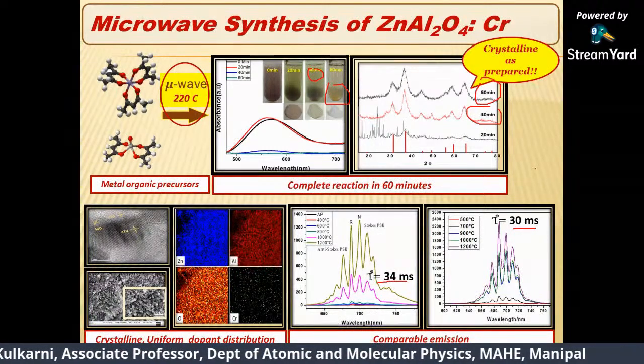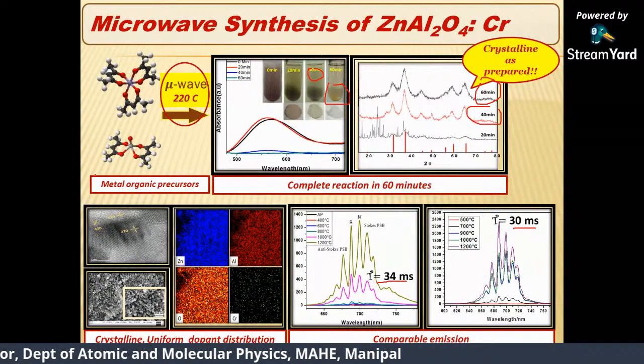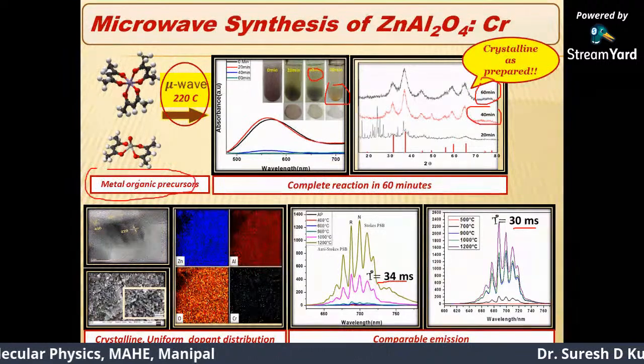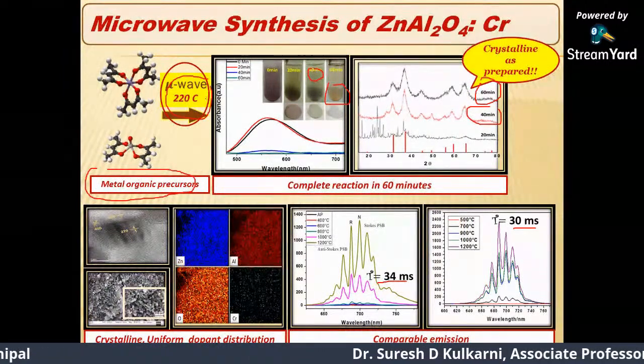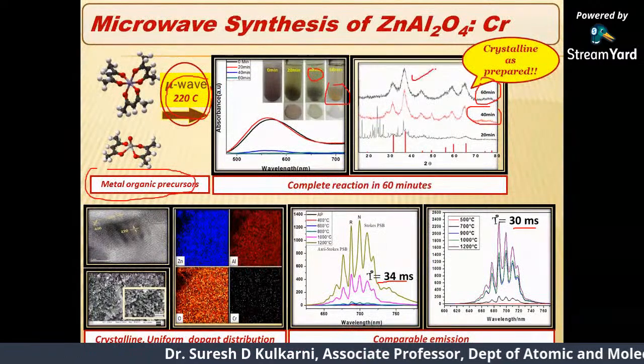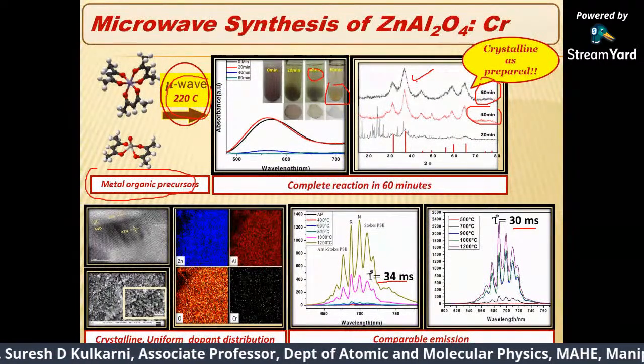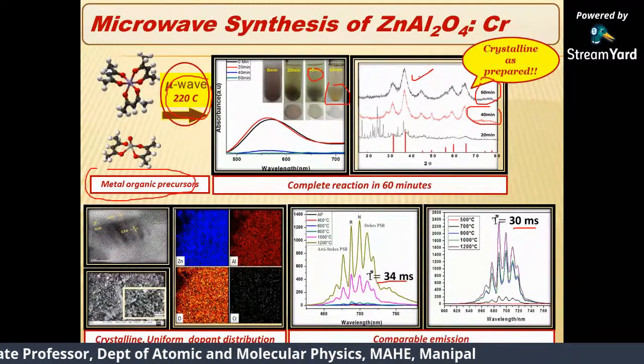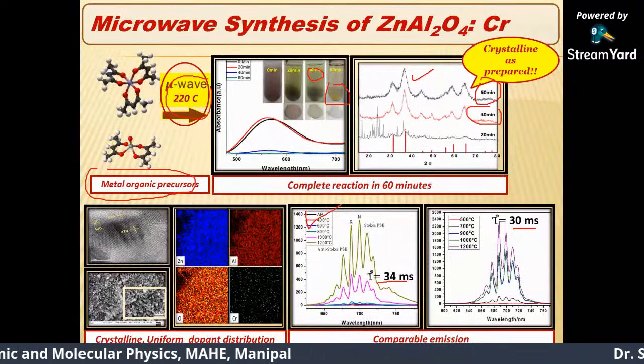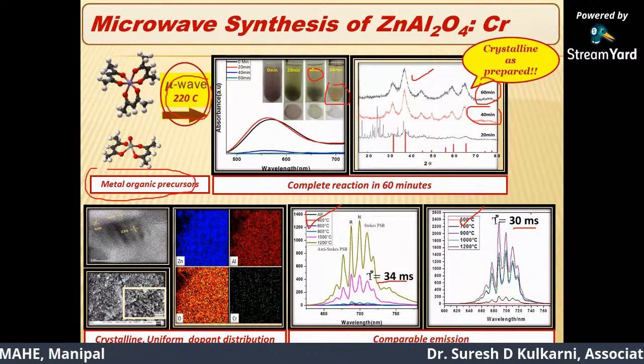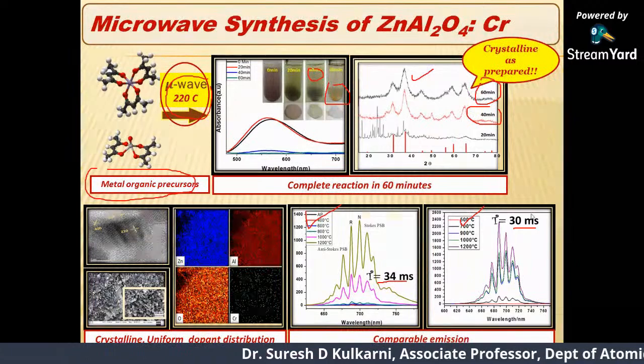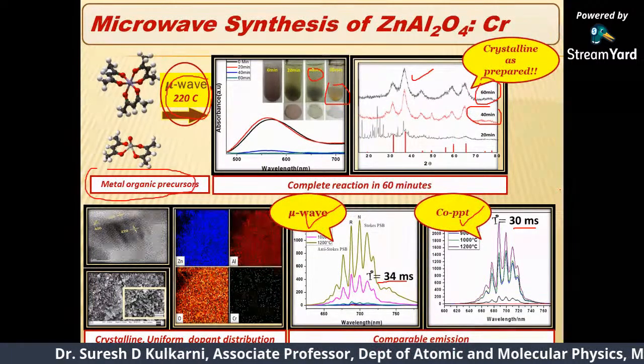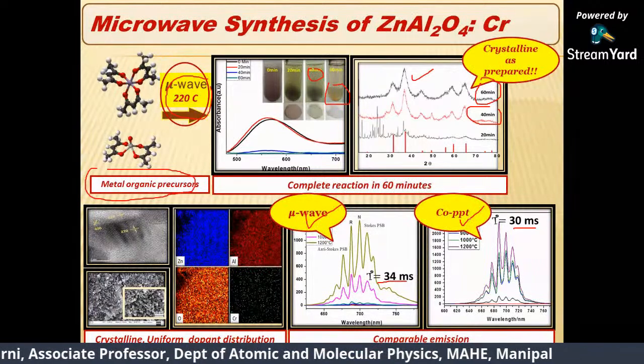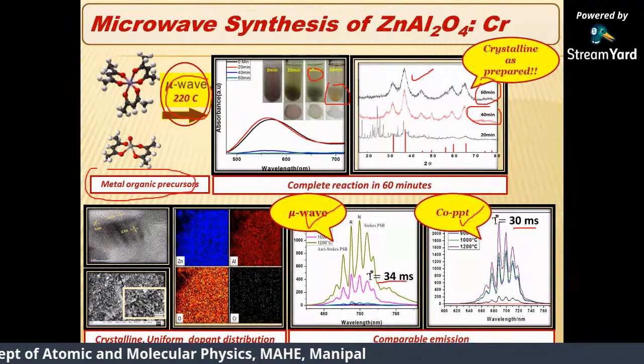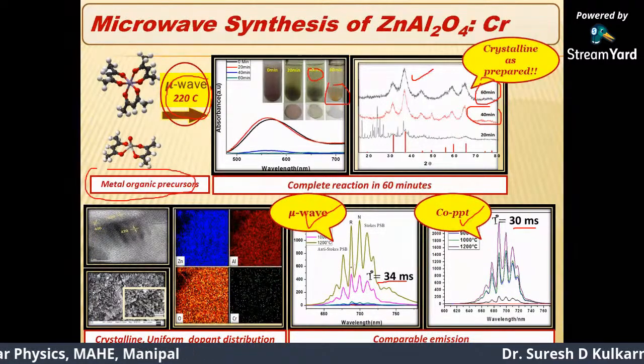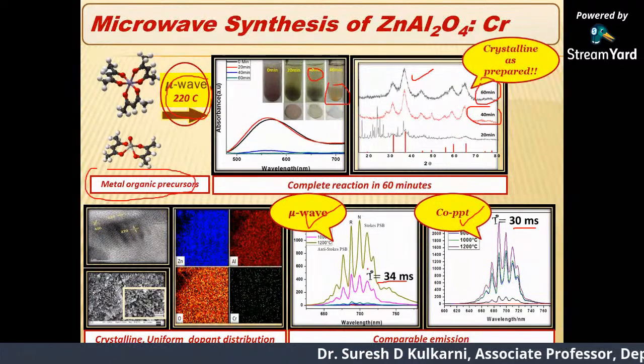The common thing in the last two slides is that we are using metal organic precursors, we are using microwaves, and lower temperatures for synthesis. The material prepared is crystalline. Already I have formed the nanoparticles of my interest, and later we are tailoring the material properties by giving different temperatures. You can see the emission properties are compared. In an earlier slide I showed we prepared the same material using co-precipitation. Now we compare with the microwave, and you can see the material can be prepared using microwave in a very quick time.